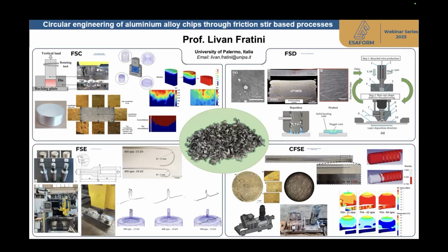Well, the idea was just to give you an overview of different processes for which actual recycling of metal chips, in this case aluminum chips, can be carried out, and to give an overview of different approaches and also new trends in terms of combination of recycling and deposition of material, with approaches characterized by solid bonding phenomena, no melting at all, trying to maintain a quite good level of mechanical characteristics, even at a local level, even in definitely difficult zones of the recycled product, both in terms of billet and in terms of wire.